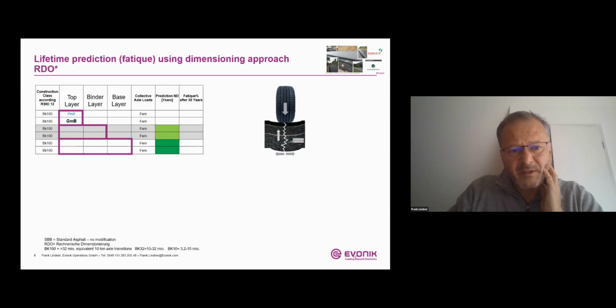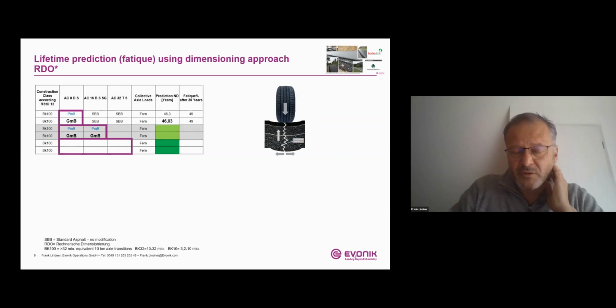We did this with top layer, binder layer, base layer. As I said, all from commercial production. Rubber asphalt was coming from the dry process, and we compare by modification of only the top layer, while the other layers had been unmodified. And we have seen that the prediction of lifetime is equal. So if only modification of the top layer occurs, then the rubberized asphalt solution is on the same quality level.